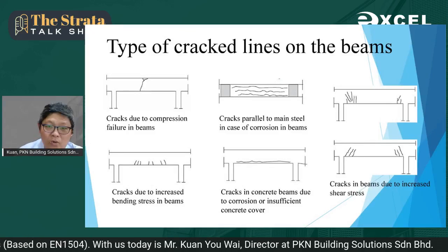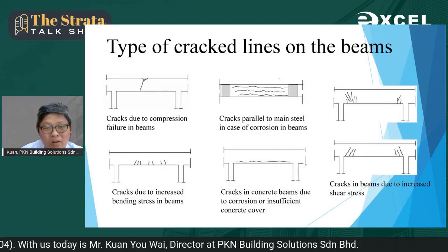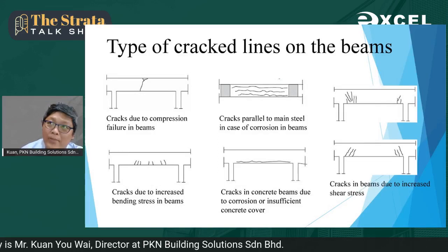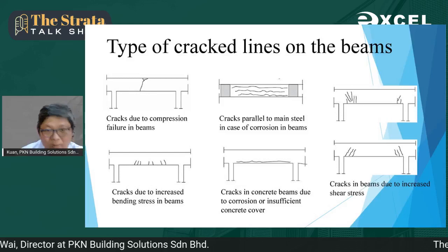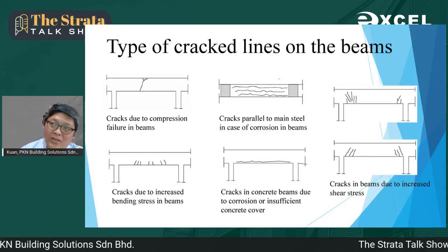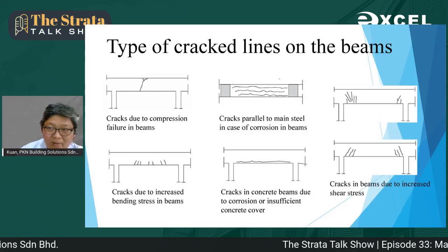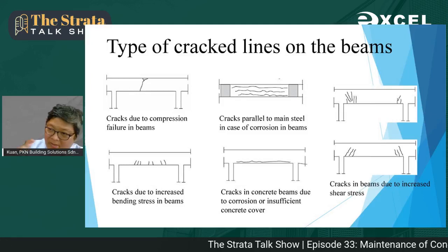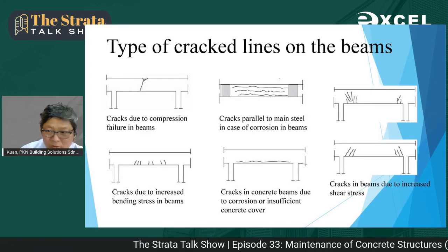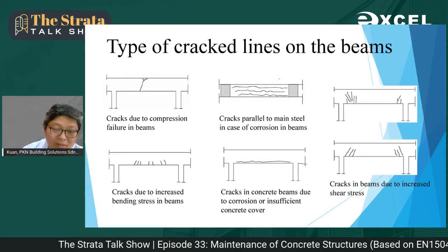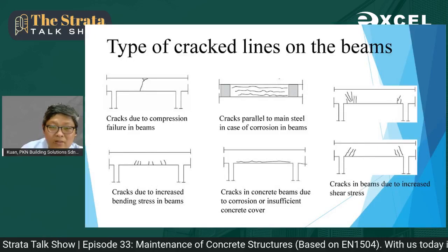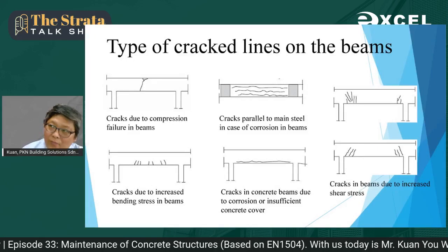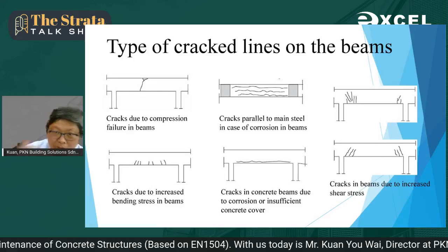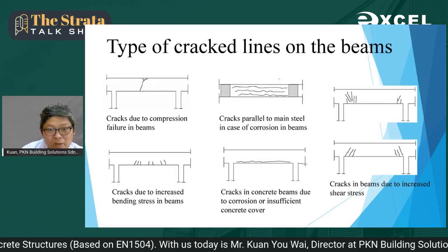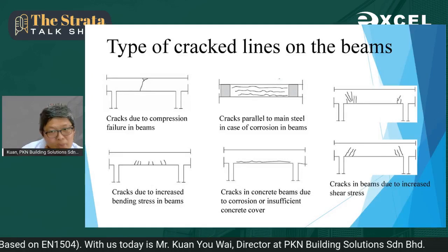And of course, corrosion risk, the corrosion crack, which happens along the reinforcement steel bar, because once the reinforcement steel bar starts to expand, it will crack the concrete cover, which is the thinnest surrounding it. So it typically can be seen along the reinforcement steel bar in a very clear pattern, and this is also dangerous.